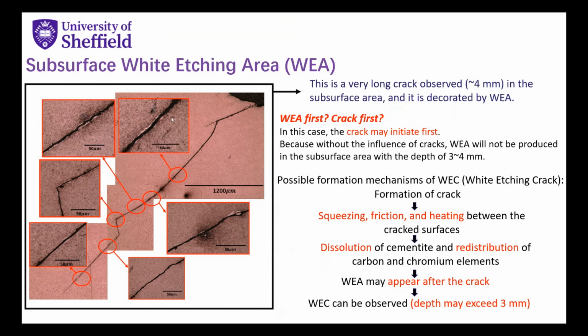At the moment, we still don't know which one forms first, the WEA comes first or the cracks first. We still don't know. But in this case, I think the crack may initiate first, because if we look at this picture in detail, we can see the white etching area in a very deep area. It's about 4 millimeters below the surface. And I think without the influence of cracks, the white etching area will not be produced in such deep area, because the effect of loading on the surface may only affect the region like 1 millimeter below the surface, but this one is about 4 millimeters, so it must be the effect of cracks.